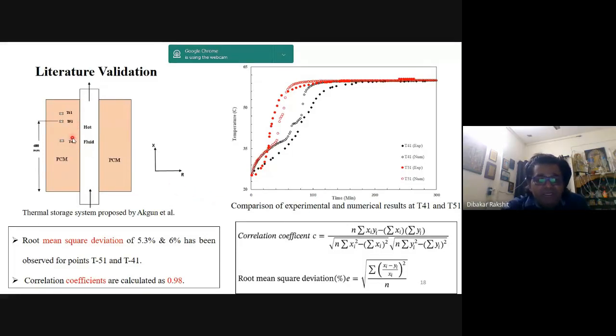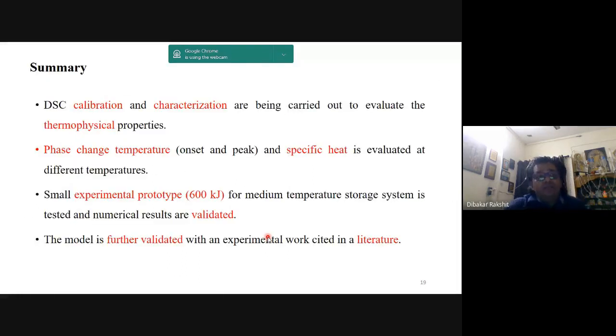Again we estimated the coefficient of correlation for each of those temperature locations where we were measuring the temperature, as there were some initial experiments done by other scientists, so we took those into account. So in this first part, we did a proper characterization of the thermophysical properties, say the heat storage capacity of that eutectic mixture which was designed for making the thermal energy storage device. We estimated the peak and onset liquefying as well as solidification temperatures, and we also evaluated the heat storage capacity of that eutectic system. Finally, we designed an experimental prototype.